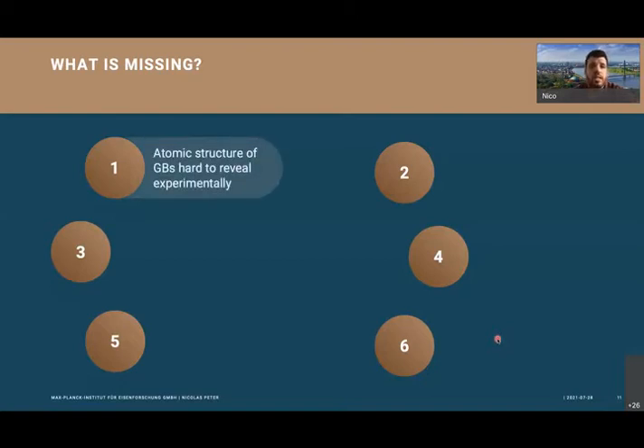First of all, the atomic structure of grain boundaries is very hard to reveal experimentally because it's so small, and because even in transmission electron microscopy you need very special conditions for the grains to be oriented in a certain way. Second, grain boundary transitions are even harder to observe at atomic resolution, because usually that involves some atomic shuffling, something is moving. So you have to have a very well-controlled experiment and a very well-controlled machine. Drift, for example, at the lowest rates might kill your experiment. In TEM, a little vibration might kill all your images.